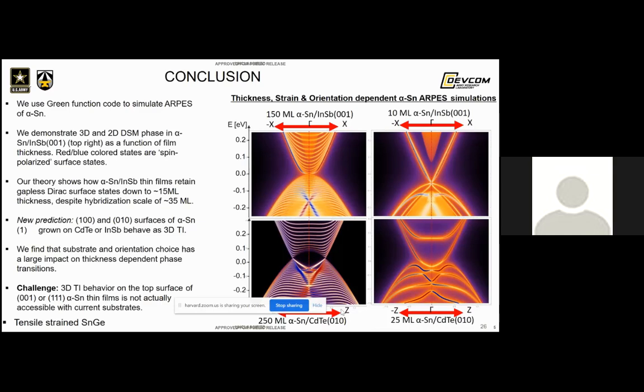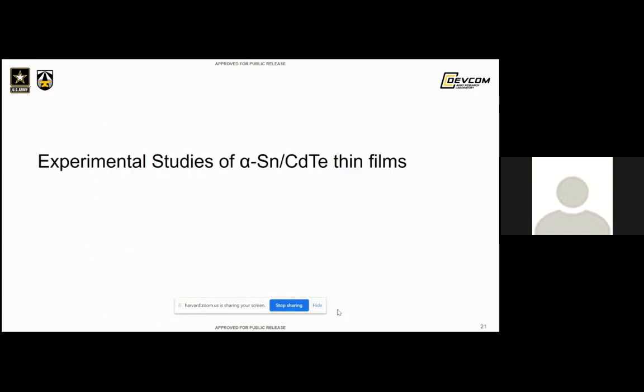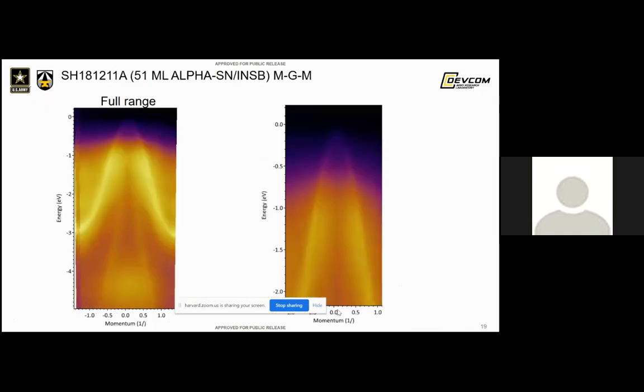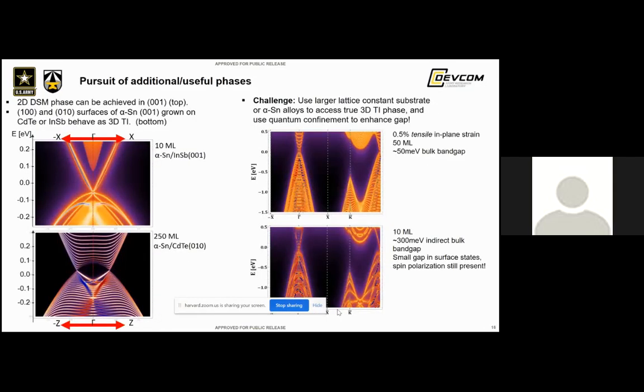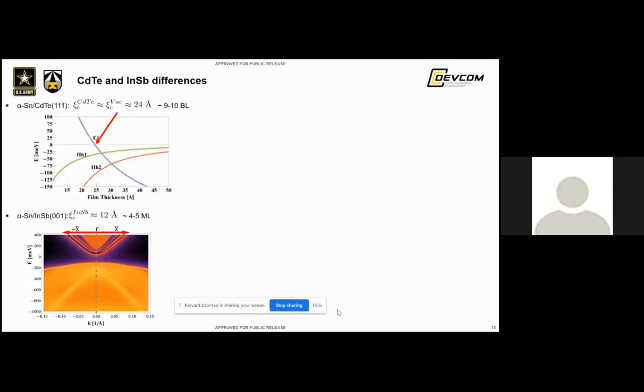So coupled to that, with the fact that you have a very small band gap in indium antimonide, those two effects combine to give you a very weak, actually almost no topological surface state on the side that faces the indium antimonide substrate. So there's very little hybridization going on between the lower substrate-side surface and the upper surface.